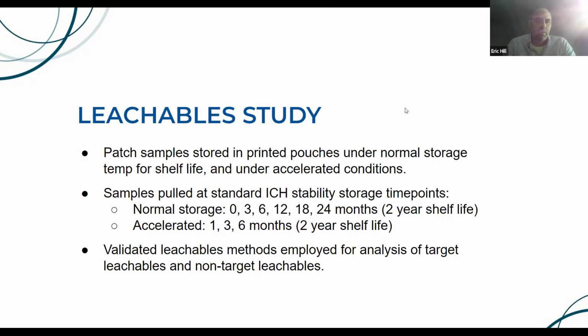Typically for normal storage, this could be 0, 3, 6, 12, 18, 24 months for a 2-year shelf life batch. And then under accelerated conditions for 1, 3, 6 months, for a 2-year shelf life. And those could be adjusted depending on the shelf life of the patch if it was not 2 years. And then we're going to employ our validated leachables methods to analyze those target leachables, as well as any non-target leachables that may develop in the patches.